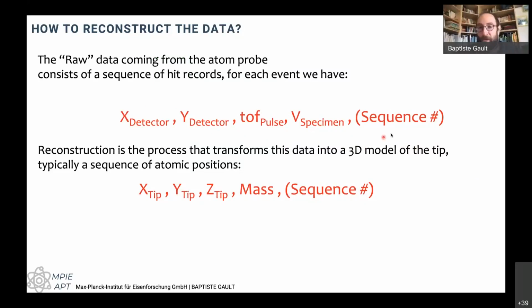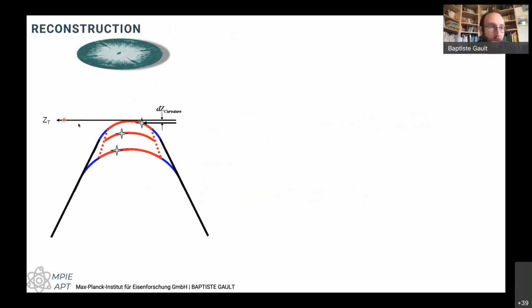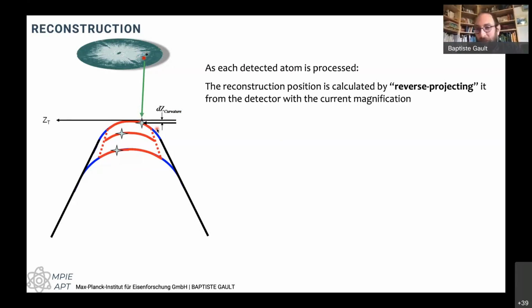So we make an assumption that it's true. But if we do this, we can use that sequence to progressively build the third dimension. So that's what we do. We assume that the ion is basically emitted by a virtual emitting surface. And then we take the position of the ion impact on the detector, and we reverse project it onto this surface using a typical projection law. So we use something that is a bit like a stereographic projection, which you might have heard of. It's not exactly right, but it's not so bad.